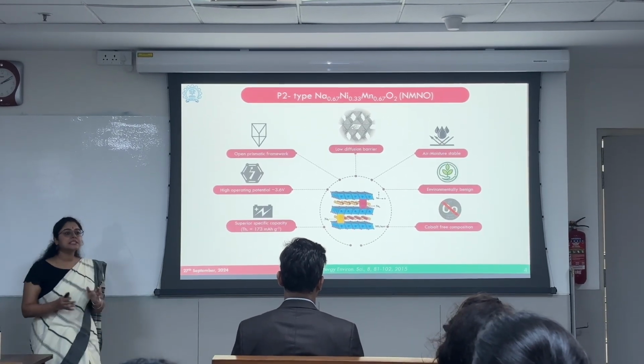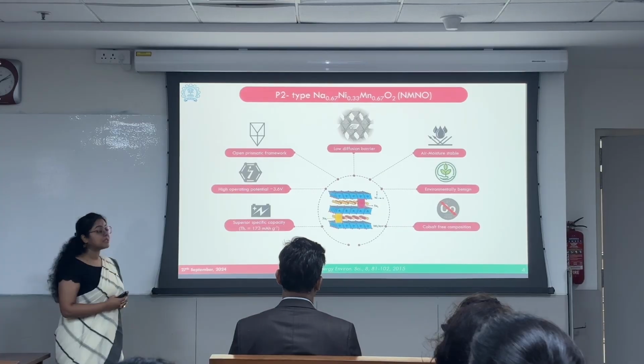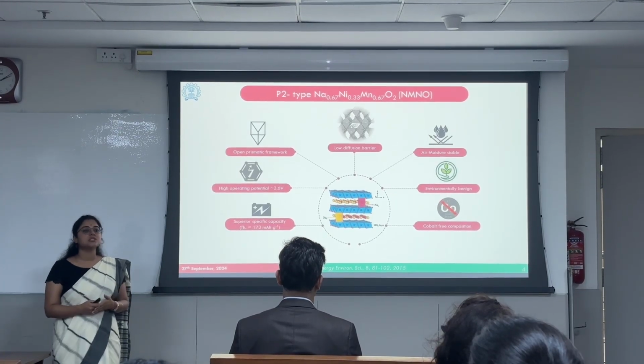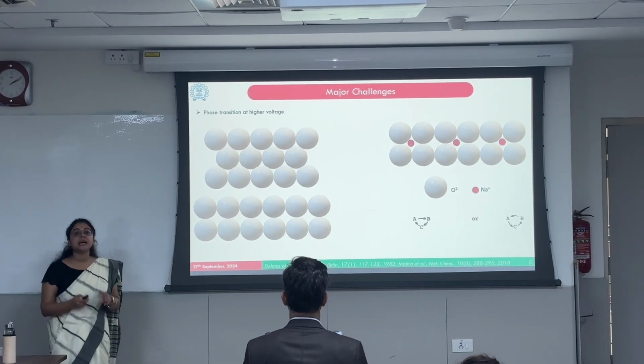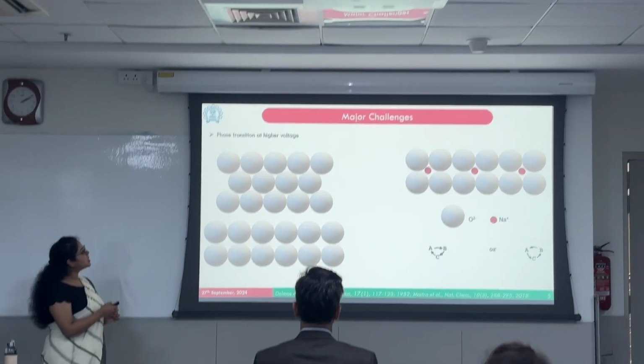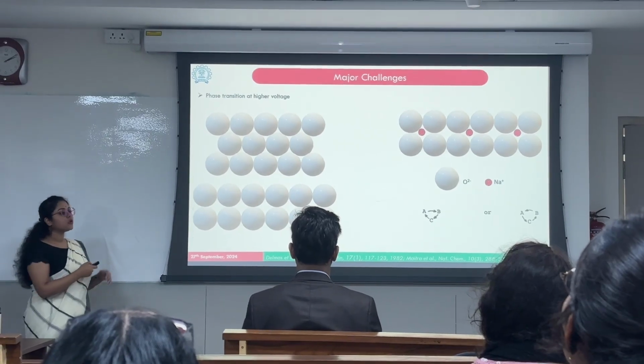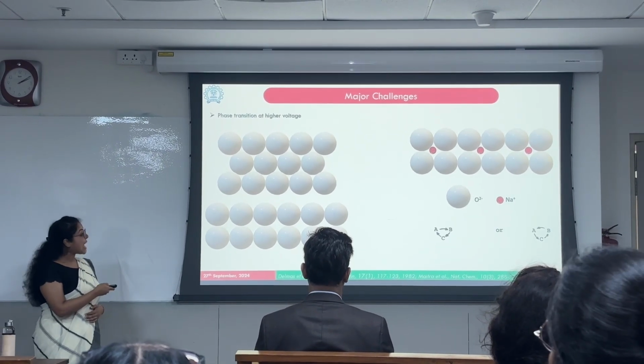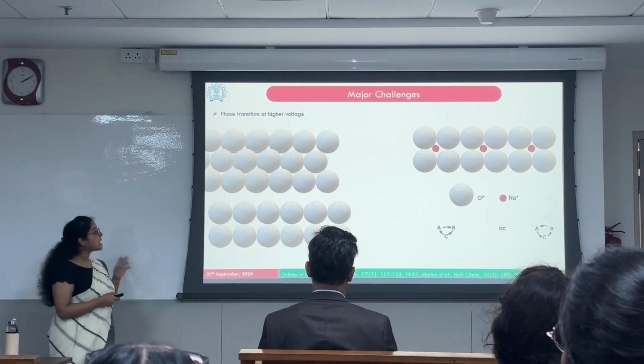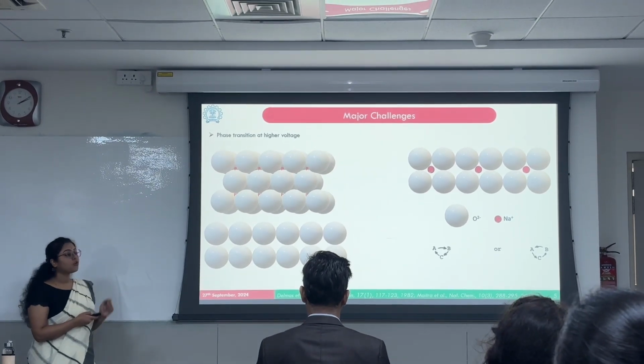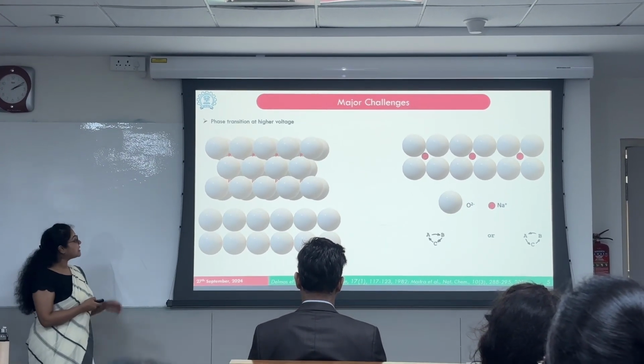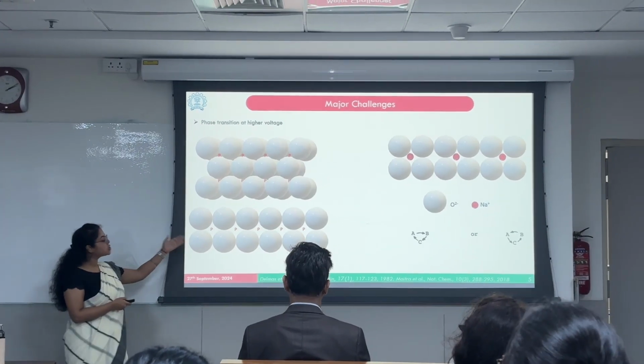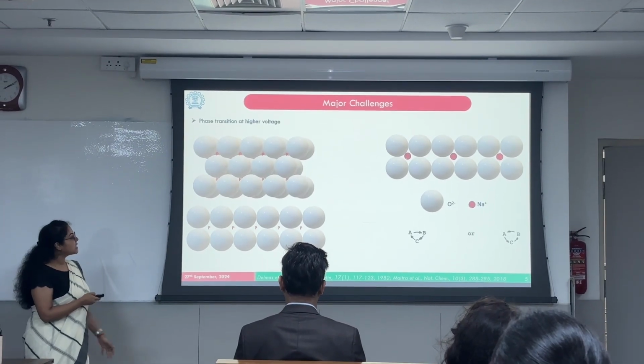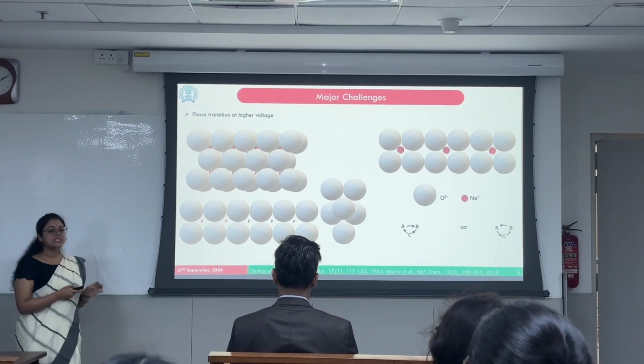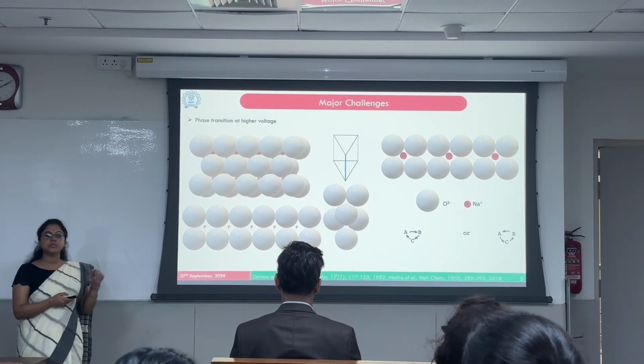In spite of having these advantages, this particular cathode material is still far from commercialization because of certain hurdles. The major one being phase transition at higher voltage. So if we visualize the first particular layer of oxygen ions in this manner, and then position the next one exactly above the other, the voids that form are prismatic voids. And the front view would look like this, in which we have inserted the sodium ions.